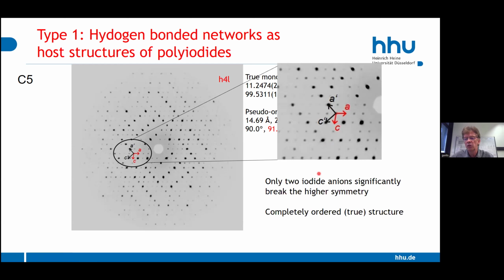If we take into account all these weak reflections, we really have a small deviation from this substructure situation. We only have 2 iodide anions that significantly break the symmetry. And of course, the organic molecules a little bit break the symmetry. The advantage of this true structure is that we always have then an ordered structure. So as a take-home message, if you have a really ordered structure without any disorder, you can be pretty sure that it's a true structure. If you have somehow a disorder, you should always be a little bit suspicious.